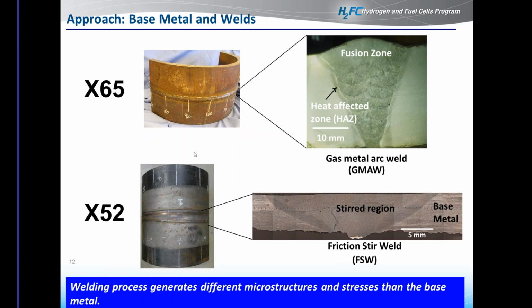Now, the other pipe we looked at was an X52 pipe, and this was also girth welded, but this was girth welded using friction stir welding. And as I mentioned, the welding process is completely different. There's actually no melted metal. It is actually just friction produced by the stirring process that softens the metal and allows it to mix. And so the resultant microstructure is actually quite similar to the base metal. And so we looked at these different microstructures between the base metal and the weld.